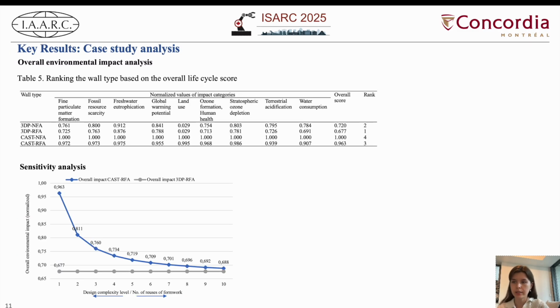To evaluate the overall sustainability of each material and method, we used the overall performance index, like rank. This index combines and normalizes all impact categories across ecosystems, resources, and human health dimensions. In our study, all categories were equally weighted, and the results show that the 3D printed wall using recycled materials had the lowest overall environmental impact and ranked first. Compared to casting, 3D printing reduced the total environmental impact by nearly 30%, and the use of recycled aggregates contributed an additional 6% improvement.